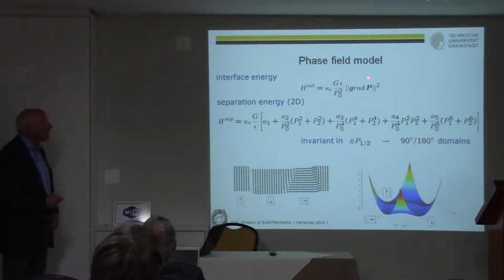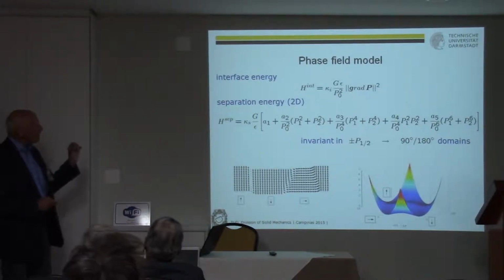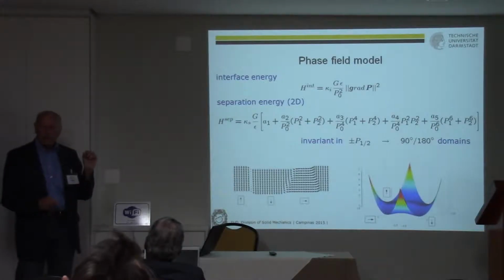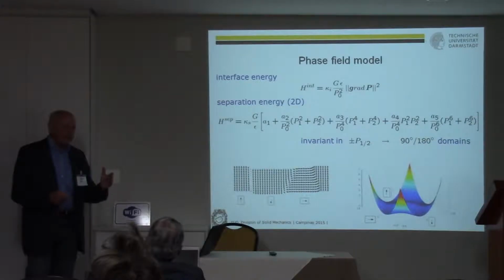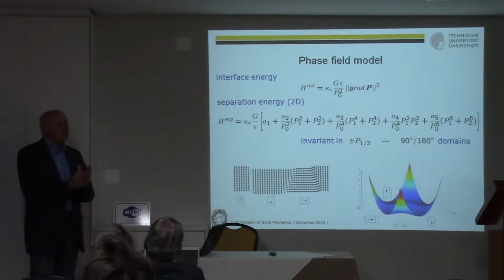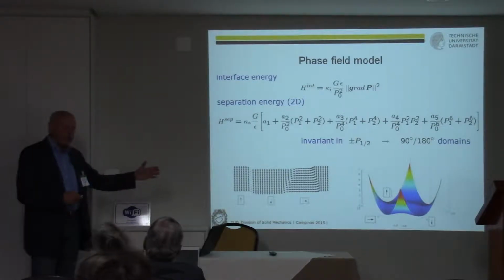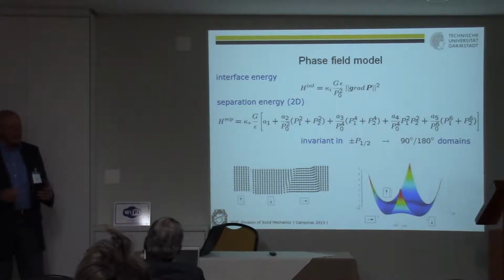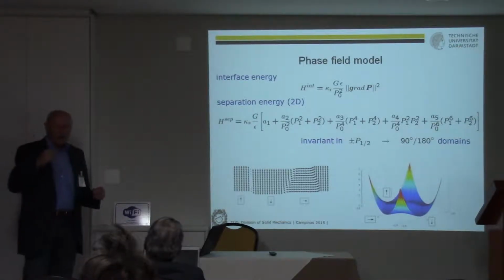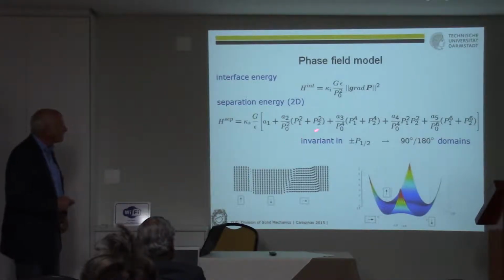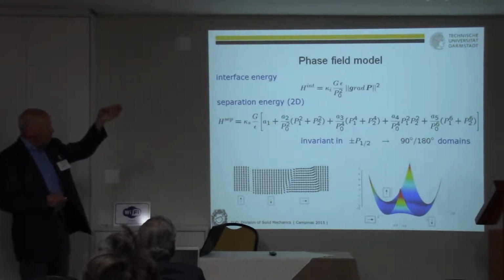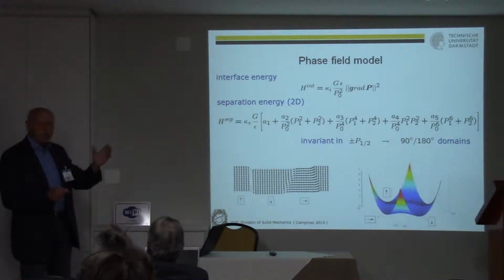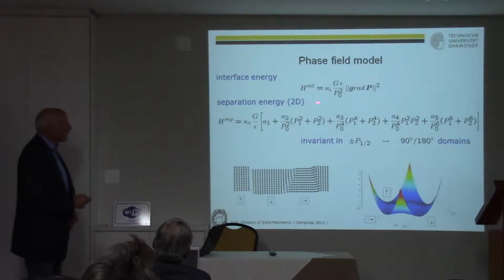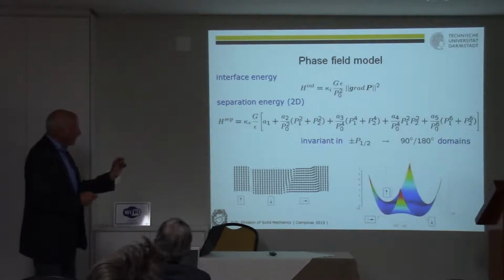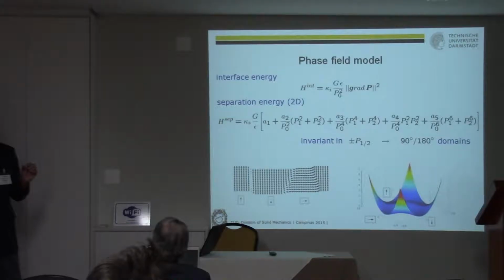Then the interfacial energy is given by this equation here, where some parameters appear, and I have not the time to explain each parameter, but essentially they describe the thickness of the domain wall. It's a field theory, and you don't take into account, say, a sharp domain wall. You can do this, but then you don't work with phase field theory. The phase field method is a field theory where all fields are in some sense smooth, and so the gradient of P replaces this jump over the domain wall. So these parameters epsilon and so on characterize the width of the domain wall.